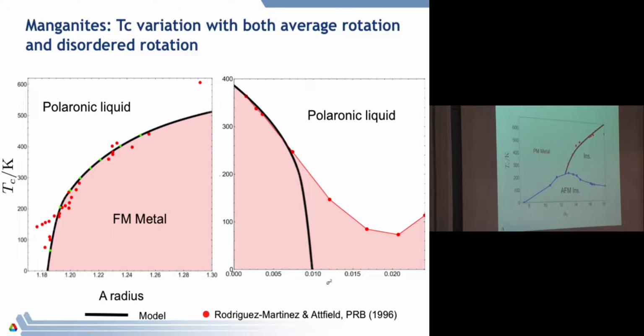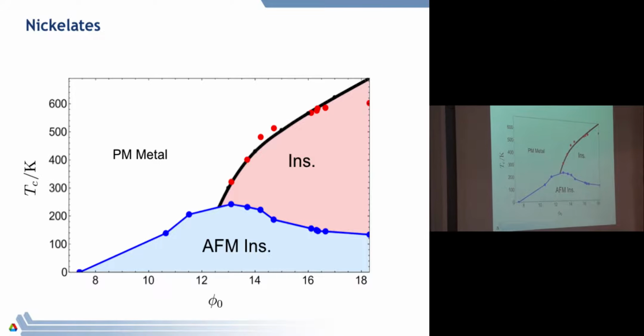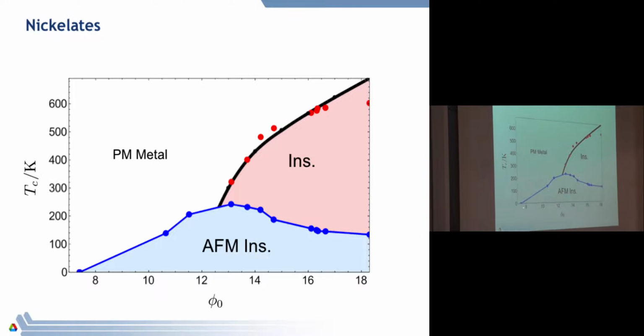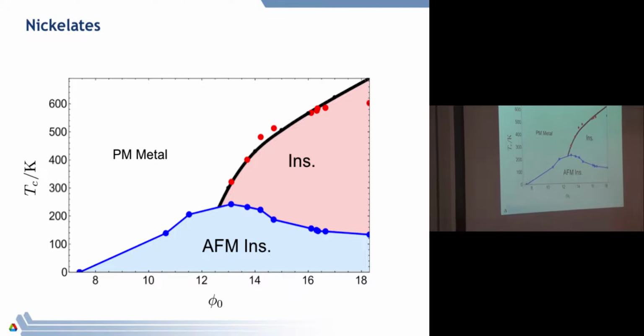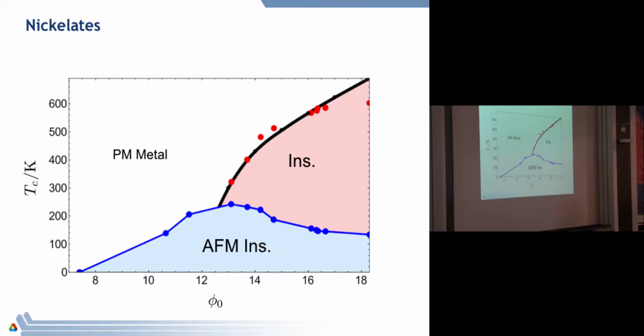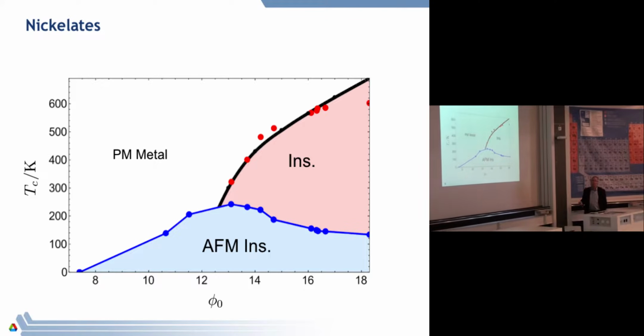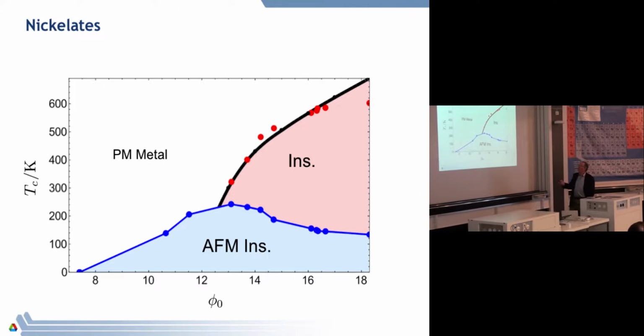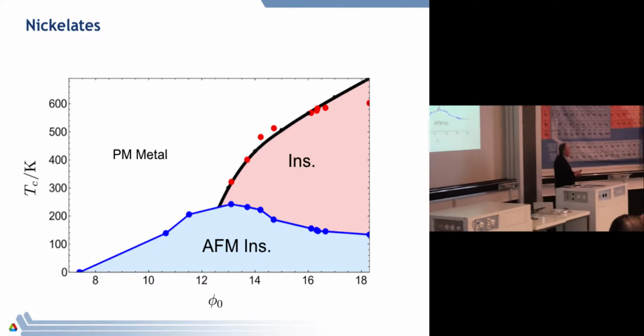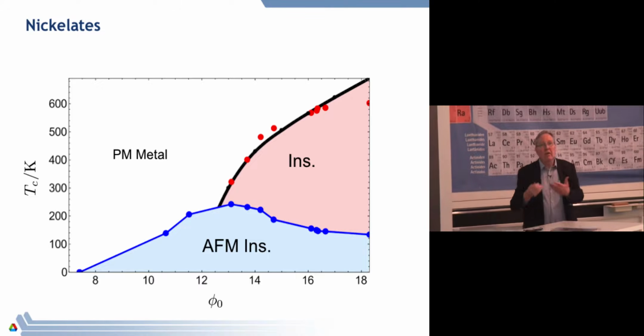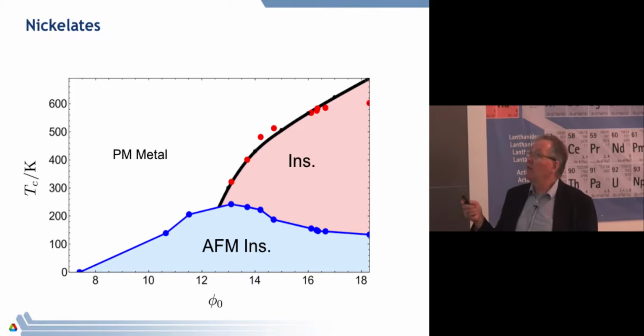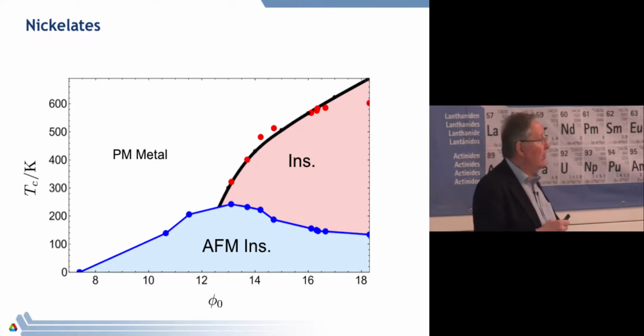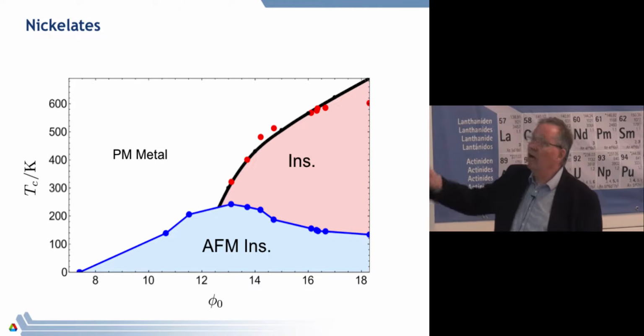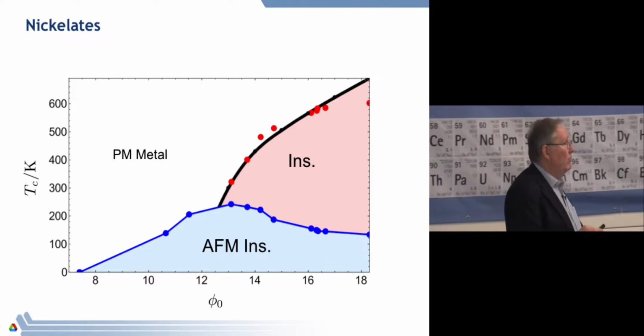Okay. Similarly, the other place where there's a lot of data is in the nickelates. Again, lanthanum nickelate is over here, and there's an insulating to metal transition, which has nothing to do with the onset of magnetism that happens at a lower temperature. And again, you can quite easily produce these very large fluctuations. But in particular, what you have here is that the elastic effects are really controlling the entropy and the entropic fluctuations associated with that, and producing these very big effects and these transitions that you can move around a lot, actually, by strain.